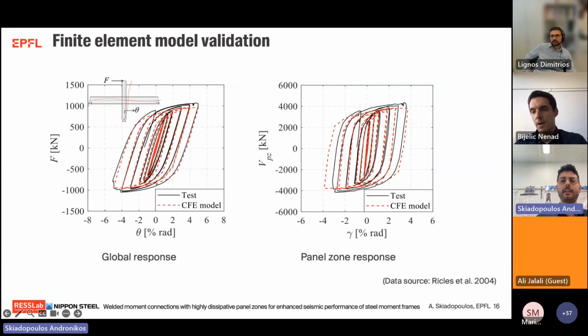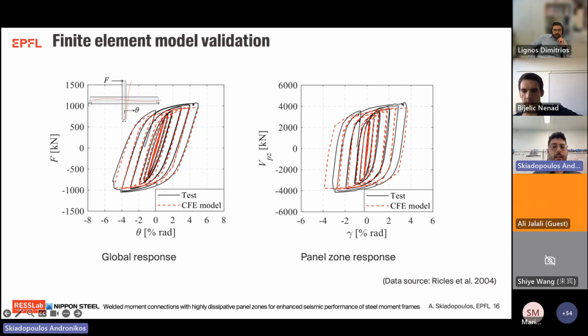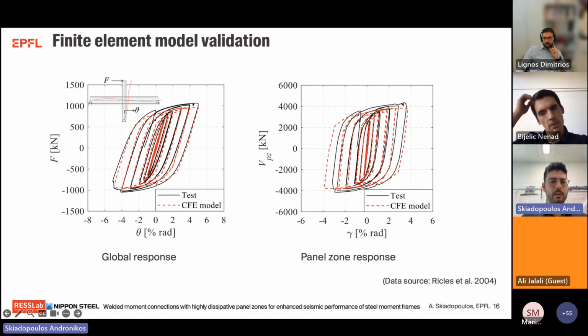The comparisons between the test and the continuum finite element analysis models are highlighted in this slide. On the left side, we see the global connection response in terms of column shear force versus story drift ratio, and on the right side, we see the panel zone response in terms of panel zone shear force in the vertical axis versus panel zone shear distortion, or shear angle, in the horizontal axis. What this slide suggests is that the modeling assumptions we made are capable of accurately capturing both the global as well as the panel zone hysteretic responses, and therefore these modeling assumptions are utilized hereinafter for the panel zone model development.